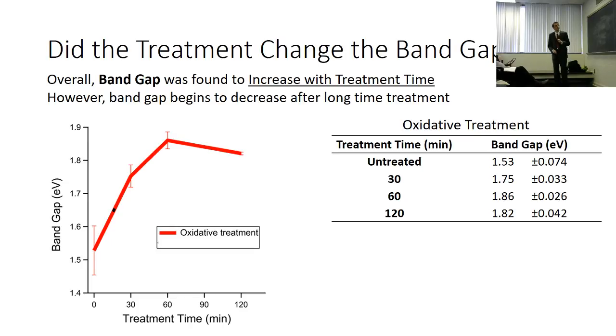So I did that, and what I found was that the band gap does change if you heat up these structures in oxygen. For the untreated sample, I found it was 1.53 for this particular sample. I took that same sample, heated it to 350 for 30 minutes, and it was 1.75 electron volts. Heated for an hour, 1.86, and then it comes down a little bit, 1.82. It goes up, and then down a little bit.